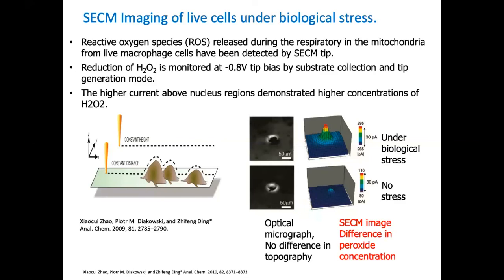It's also used in biological applications, where a lot of biologists use SECM. I'll explain this slide to you. You know that many cells, if you put them under stress, produce reactive oxygen, hydrogen peroxide. But if you see a normal micrograph of this particular cell, you don't see any difference. But in SECM measurements, SECM is probing hydrogen peroxide, which is the reactive oxygen produced when the cell is under stress. And where is it produced? Near the nucleus of the cell. So using SECM, one can immediately find out, under stress, which part of the cell is active. It's a very important application of SECM.